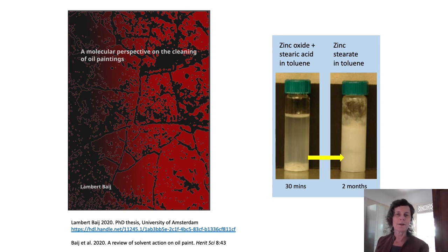As previously shown, the solubility of stearic acid in toluene enabled rapid reaction with zinc oxide to form soaps. In a painting, solvent and fatty acids in solution are obviously more constrained in their movement. However, solvent diffusion has been shown to enhance fatty acid transport through the binding medium.